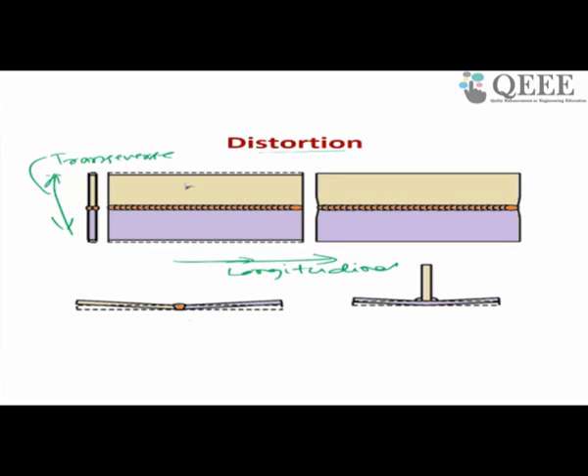In welding, the distortion may happen in the transverse direction, so it has contracted like this, or it may also happen in the longitudinal direction. Initially it was the total initial length. Because of the residual stress, it distorted. So this is called distortion. It is a structural defect. Or it may also be angular. If you do not support properly during welding, what will happen? When you allow it to cool, contraction will happen. When you do not allow that to happen, then residual stress will be developed. If you allow that to happen, then distortion will happen. So angular distortion can also happen.